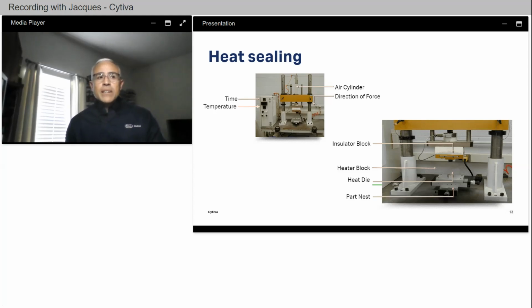Now, with the heat sealing, it is possible to form two different types of bonds. The first type occurs if the filter and the housing material have similar thermal properties. In this type of seal, the material and the housing will melt together to form a molecular bond which is very secure. The second type of bond occurs when the housing material melts at a lower temperature than the membrane. In this situation, the molten plastic from the housing penetrates the structure of the filter material, forming a mechanical bond. And this type of bond relies on the strength of the plastic that interconnects with the physical structure of the membrane.